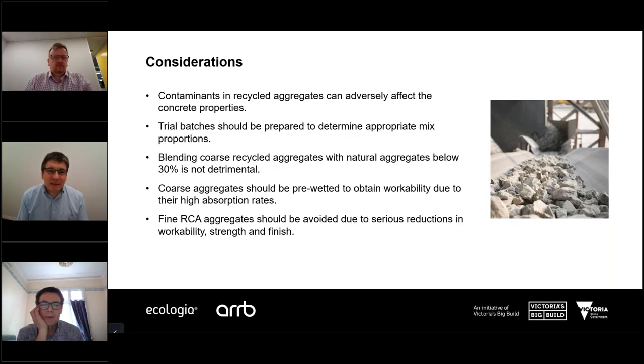As I said, it's an engineered material, and we need to meet specifications and have good construction quality. So trial batches are important to understand how this material mixes and how it goes down. As Michael Moffat mentioned, blending of recycled aggregates with natural aggregates is a good thing, and there's specifications around that and limits on what can be done. And good practice is to pre-wet these aggregates due to their high absorption rate. So when you're determining your optimum moisture content for compaction, you need to take that into account. And it's suggested that we avoid the fines because these might reduce workability, strength, and finish. Next slide, thanks.